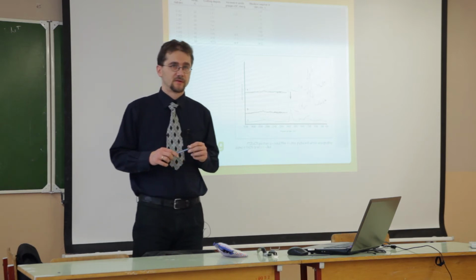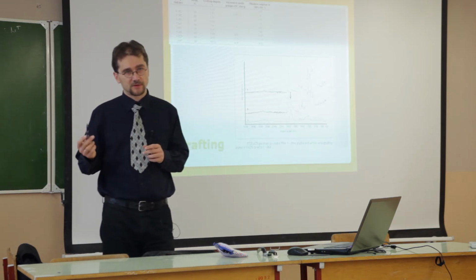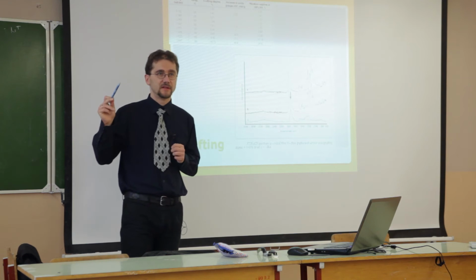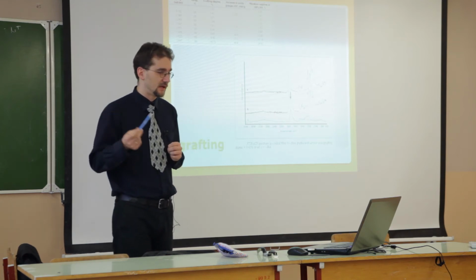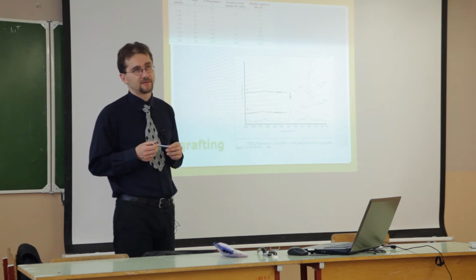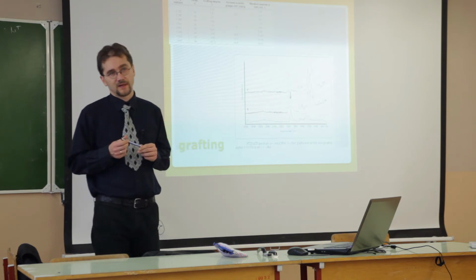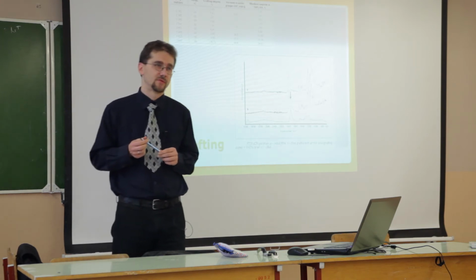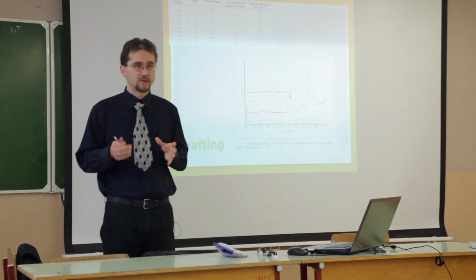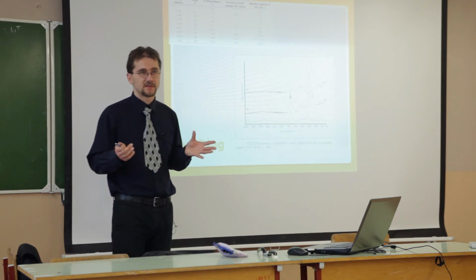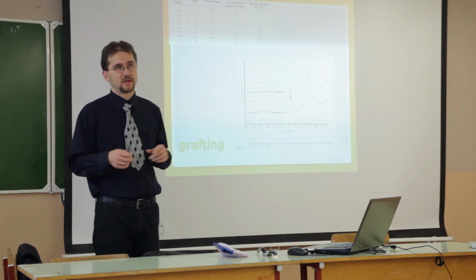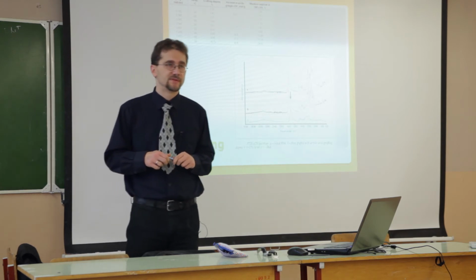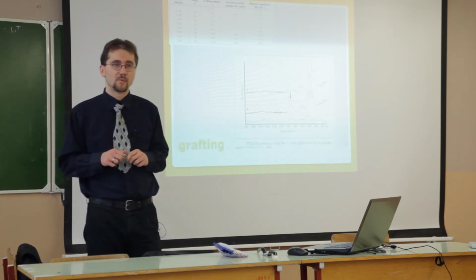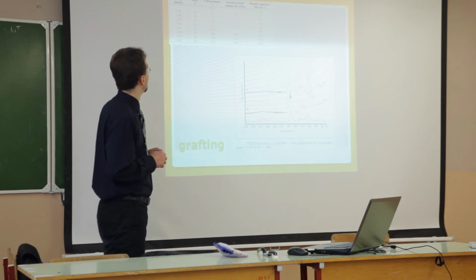We have a very thin layer on the surface after this modification, and it is difficult to find a technique that can be used for controlling this process, because regular spectroscopic techniques cannot be used here since the layer is too thin in comparison to the main material.